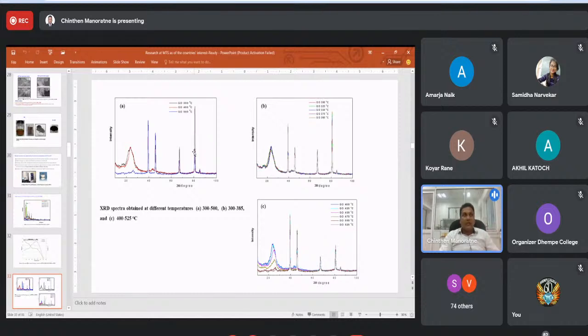Now, to understand the exact temperature where this graphite oxide is converted to graphene, we further narrowed down our temperature scanning, where we did scans from intervals like 300 to 500, and again 300 to 400, until 385, and 400 to 525. There you can see that at about 475, conversion of graphite oxide takes place. That is actually the minimum temperature required to convert graphite oxide to graphene.